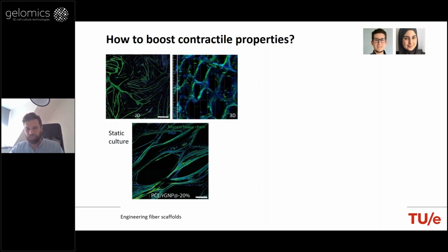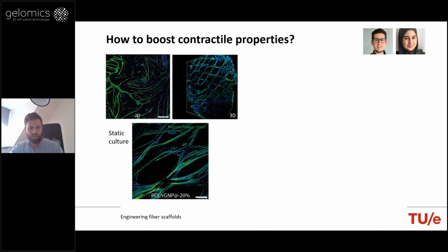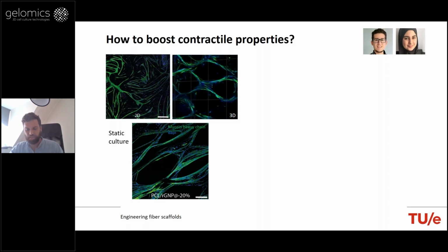We showed that this myogenic differentiation marker was significantly higher for cells grown on the 3D printed electrowritten scaffolds, when compared with the 2D cultures, as I mentioned.